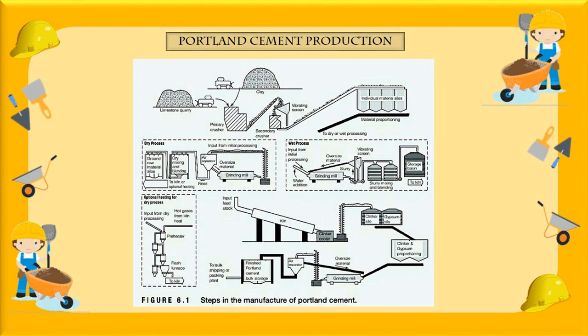The ground material is stored until it can be sent to the kiln. Modern dry process cement plants use a preheater tower cyclone to preheat the ground material, or feedstock, with exhaust gas from the kiln. In addition, some plants use a precalciner furnace to further heat the feedstock. Both the preheater and precalciner furnace improve the energy efficiency of cement production. In the kiln, the raw materials are melted at temperatures of 1,400 to 1,650 degrees Celsius, or 2,500 to 3,000 degrees Fahrenheit, changing the raw material into cement clinker. The clinker is cooled and stored. The final process involves grinding the clinker into a fine powder. During grinding, a small amount of gypsum is added to regulate the setting time of the cement in the concrete.